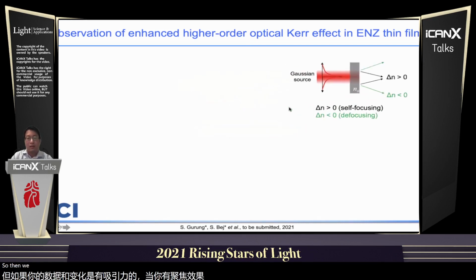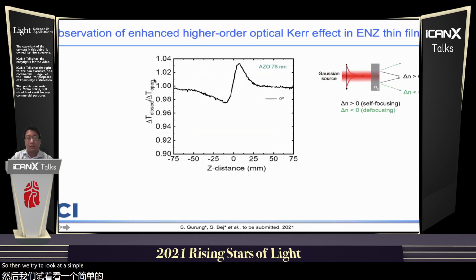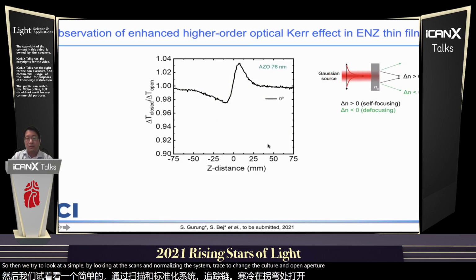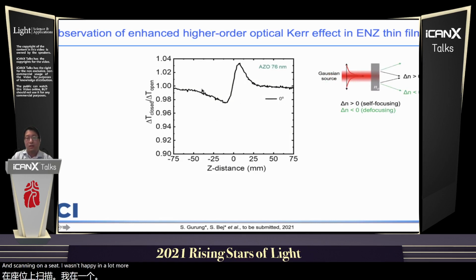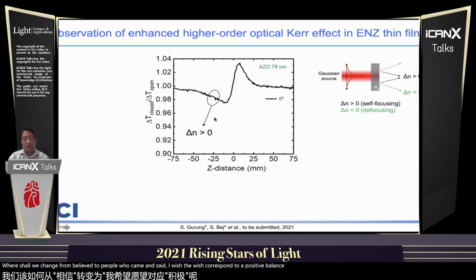So then we try to look at our sample by looking at the Z-scans and normalizing the Z-scan trace between the closed aperture and open aperture, scanning in the Z direction. At normal incidence, you will see the transmission ratio change from a dip to a peak when we scan in the Z direction, which corresponds to a positive delta N here.